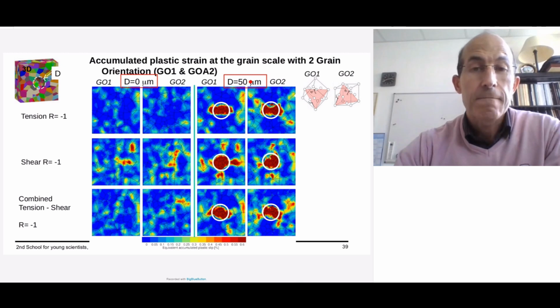Of course, the hotspots depend on the grain orientation. When there is a defect, if the defect has a diameter larger than the mean diameter of the grain, you can see that here the diameter is 50 micrometers. It is larger than the diameter of 1 grain. You can see that this defect attracts all the cumulated plasticity.